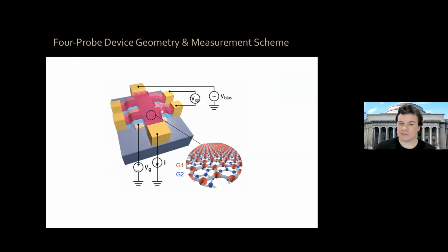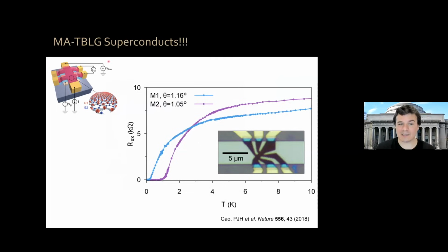So we made similar devices, okay, just with 4-terminal, in this case actually 6-terminal Hall bar geometry, so that we can run a current through the device and measure intrinsically the voltage dissipated, the energy dissipated in the bulk of the device, okay? And we made devices, and lo and behold, to our great surprise, magic angle twisted bilayer graphene superconducts, okay? You have data here for 2 devices. By now we have dozens and dozens of these devices, okay? The resistance versus temperature experiences this precipitous drop to 0, below our noise measurement floor. The system is a superconductor.